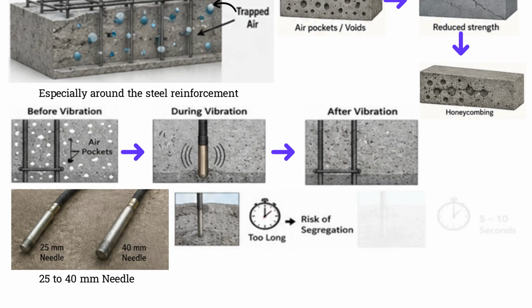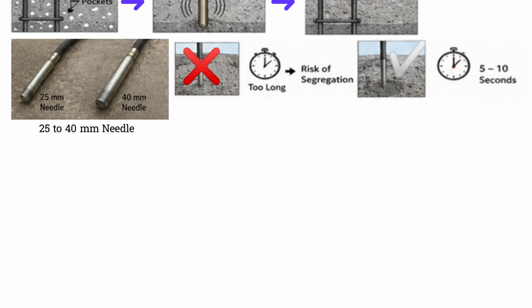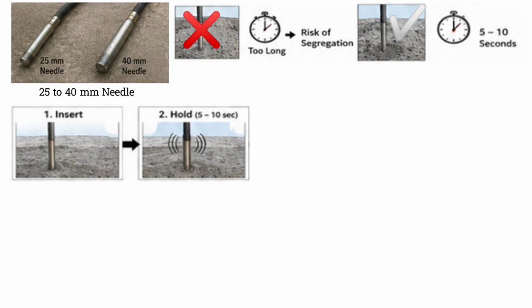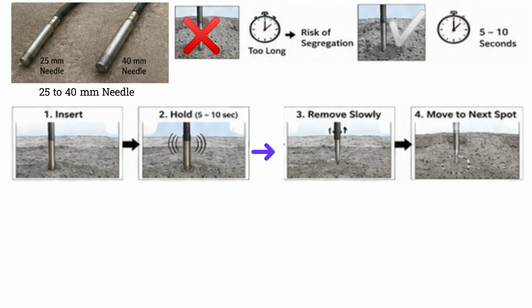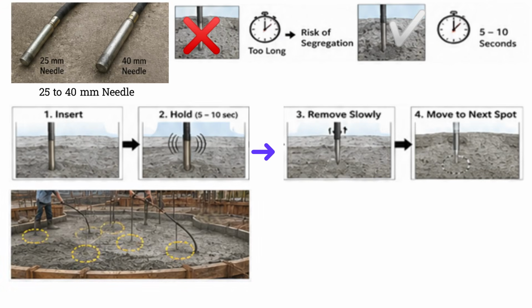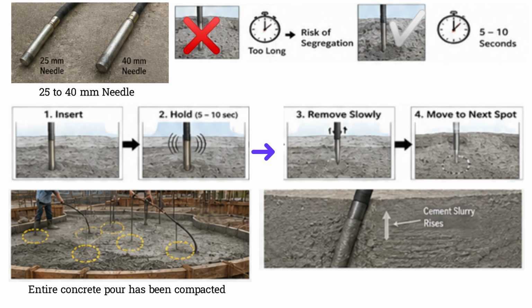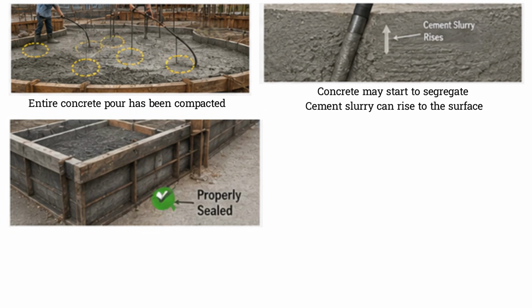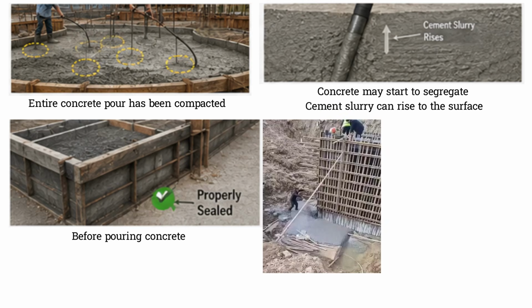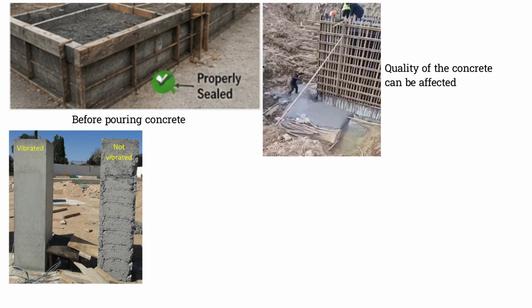While using it, don't keep the vibrator in one place for too long. Insert it into the concrete for about 5 to 10 seconds, then remove it slowly and move to the next spot. Continue this process until the entire concrete pour has been compacted. If you vibrate for too long in one place, the concrete may start to segregate and cement slurry can rise to the surface. Also, make sure the shuttering is properly sealed before pouring concrete. If cement slurry leaks out through gaps in the shuttering, the quality of the concrete can be affected. Using a concrete vibrator correctly helps produce denser, stronger, and more durable concrete.